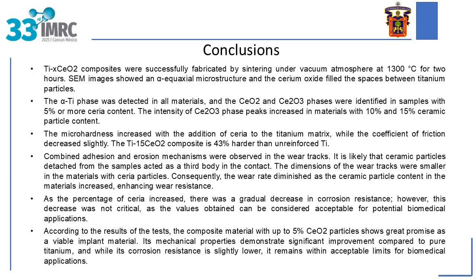The intensity of cerium 3 oxide phase peaks increased in materials with 10% and 15% ceramic particle content. The micro hardness increased with the addition of ceria to the titanium matrix, while the coefficient of friction decreased slightly. The titanium 15 ceria composite is 43% harder than unreinforced titanium. Combined adhesion and erosion mechanisms were observed in the wear tracks. It's likely that ceramic particles detached from the samples act as a third body in the contact.